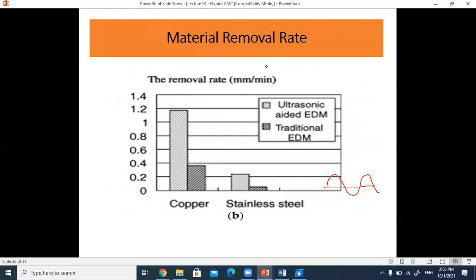So when we compare the material removal rate between ultrasonic aided EDM and traditional EDM, we can see quite a significant difference between the two. When you talk about copper, you're talking about three times better if you use ultrasonic aided EDM compared to the traditional EDM process. Similar data can be seen when you machine stainless steel. So this indicates that the material removal rate for ultrasonic aided EDM is much better compared to the EDM process.